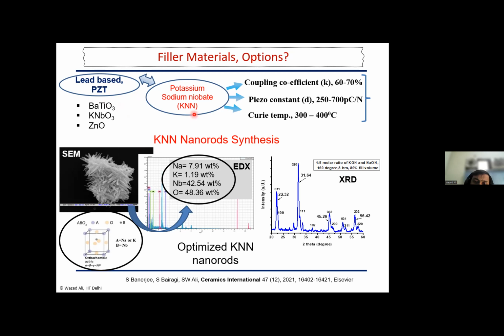which is sodium potassium niobate, and we synthesize it in terms of rods, right? So rods, why actually rods? For example, if we talk about particles, if you want uniform properties throughout the fiber structure, then particles have to be present everywhere. And if you load more and more particles in the textile structure, the fiber structure is going to become brittle and brittle, right? So we thought, can we synthesize this filler material in terms of some aspect ratio, so it can be flexible as well as a continuous deposition in the fiber structure, and at lower loading as compared to particles, we can maintain the flexibility of the structure as well as have enhanced property, right?